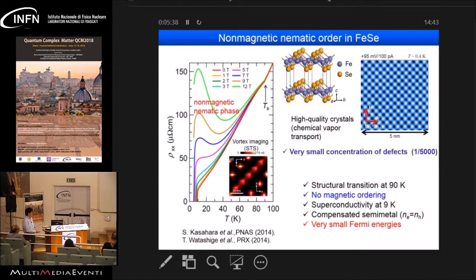It has very interesting physical properties. First of all, this is the temperature dependence of resistivity, and you have a kink at Ts, which is 90 Kelvin. This is the structural transition from tetragonal on the high temperature side to orthorhombic on the low temperature side. We have no magnetic ordering down to low temperatures, which is quite different from the other iron-based superconductors. Below Ts, we have a strong in-plane anisotropy occurring. For example, if you look at the vortex cores, they have an elongated shape along the a-axis. So we call this state a non-magnetic nematic phase below Ts. We also have superconductivity at 9 Kelvin without any doping.